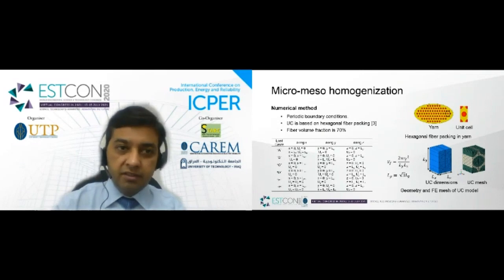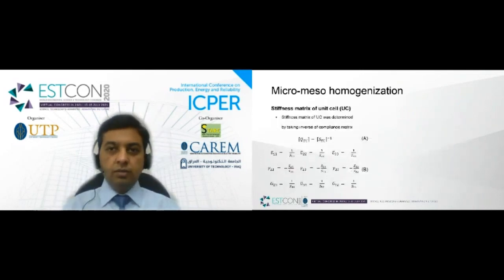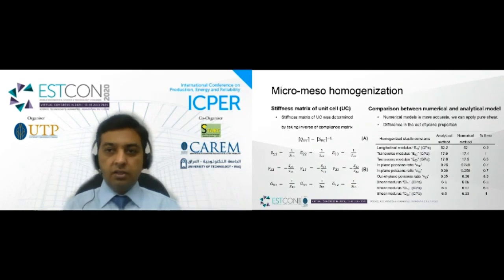In each case, displacement load was applied to get respective reaction forces, and these reaction forces are then used to determine the compliance matrix. So once we know the compliance matrix of the unit cell, the stiffness matrix of the unit cell is determined by taking the inverse of the compliance matrix using equation A. From the stiffness matrix, all the elastic constants of impregnated yarns were evaluated using equation set B. The table on the right shows the comparison of elastic constants predicted through analytical and numerical method. The values estimated by the numerical model are more accurate because we can apply pure shear in finite element analysis.